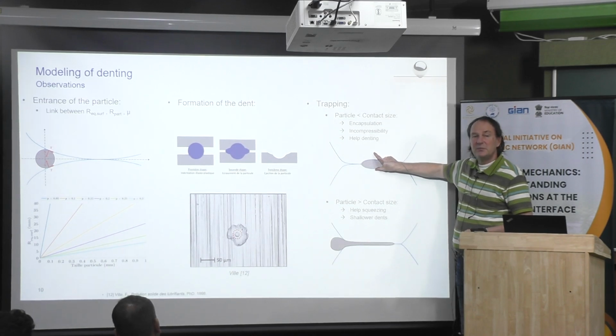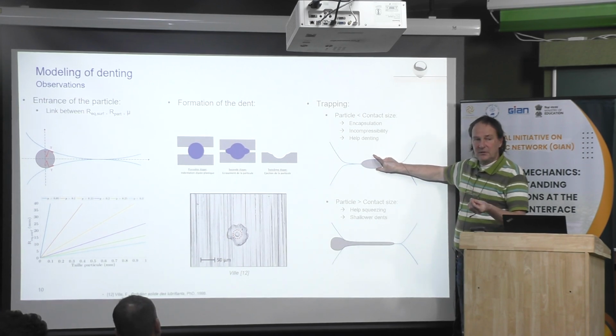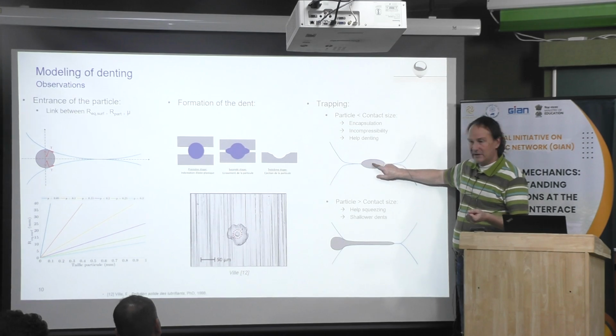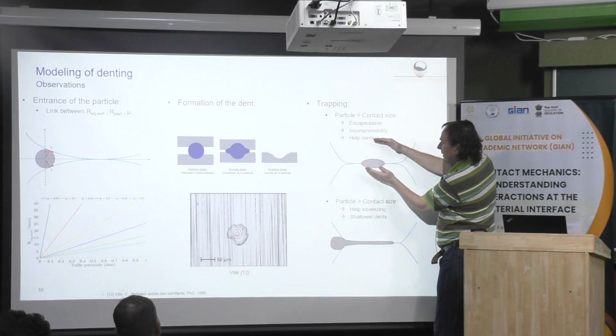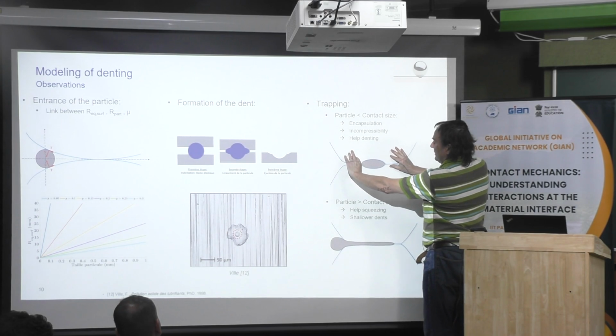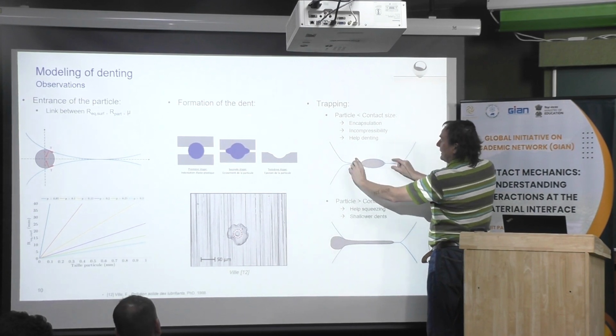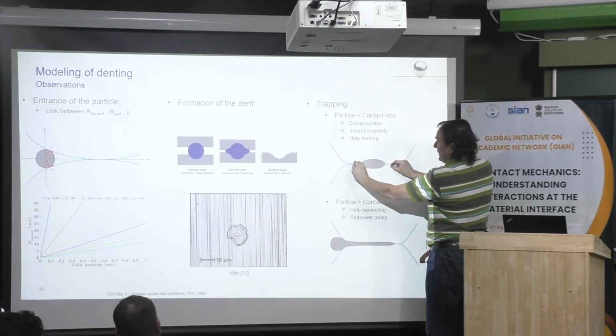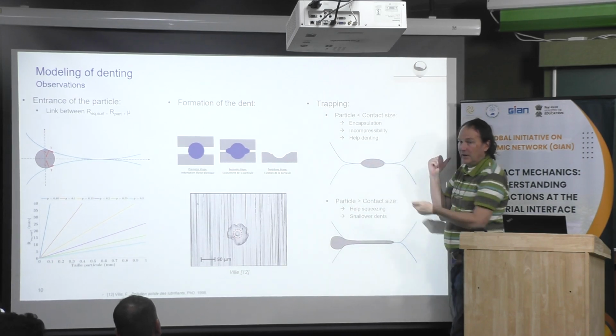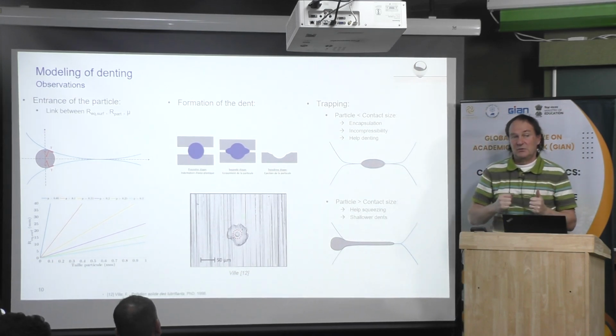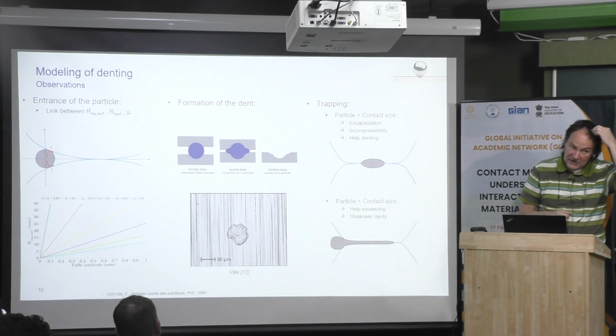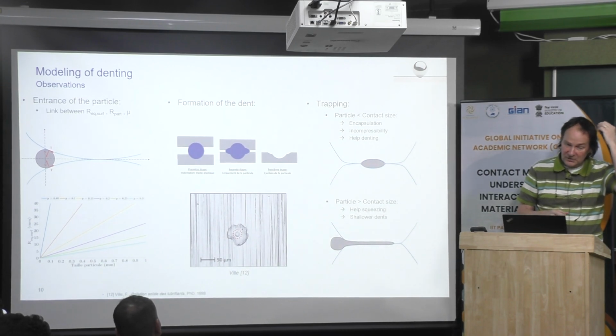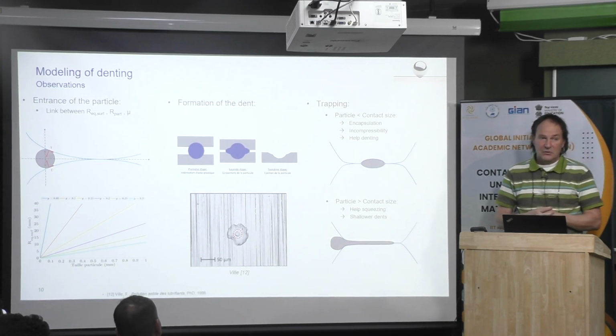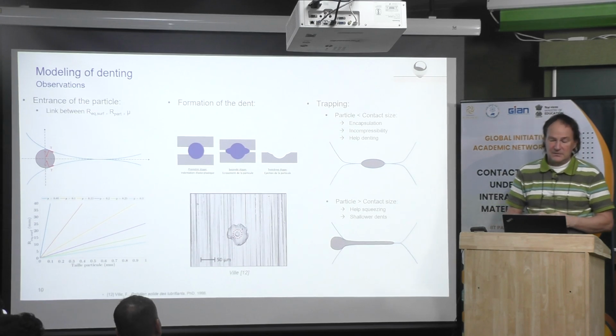Okay? Then it is not because you have something very soft in the oil, some polymer, for example, that it is harmless. It can be very critical if it is of small size, because when you deform, and as soon as you touch the surface around the dent, around the particle, it cannot move anywhere outside, and because it is incompressible, it will mark the surface. Okay? With air, for example, the same. If you have some particle like that in the oil, you can damage the surface.